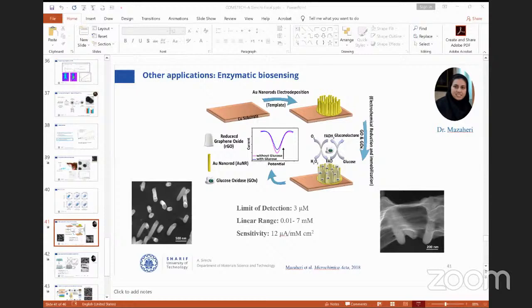One of my PhD students developed a special procedure to grow gold nanorods in an ordered structure on a template, and then loaded glucose enzyme on the surface to make an electrochemical sensor to detect glucose very quickly inside the blood of diabetic people. Okay, the result was nice, but not very outstanding compared to the other existing materials.